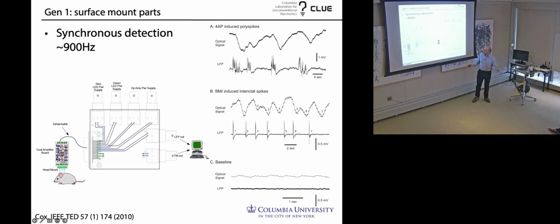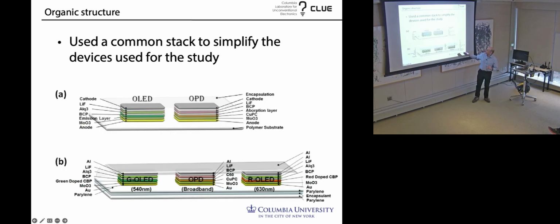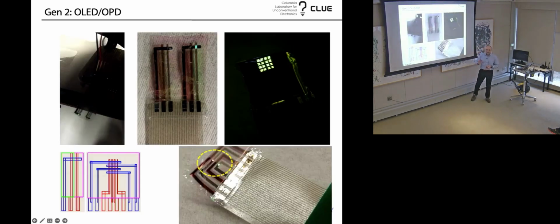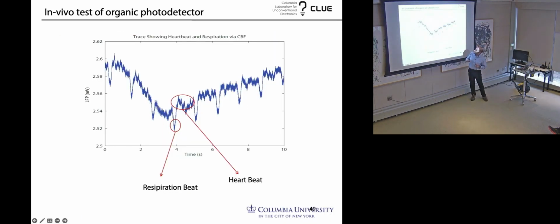Anyway, we did a couple things, and not to bore people with the early work, our first dream was to make an OLED and organic photodetector all in one go on the same substrate. What's great is that making organic light-emitting diodes and organic photodetectors is kind of like making a sandwich, where you make a P-type slice of bread, you make an N-type slice of bread, and then the filling is different, and you put the bread together. So, I'd say 80% of the process is the same, and it's really just the middle layers that were different. Then we did that on a polymer substrate, and we did some encapsulation, and you can make different colors, and you can do all kinds of things. And we can make this very flexible. We can make it very thin, and it works.